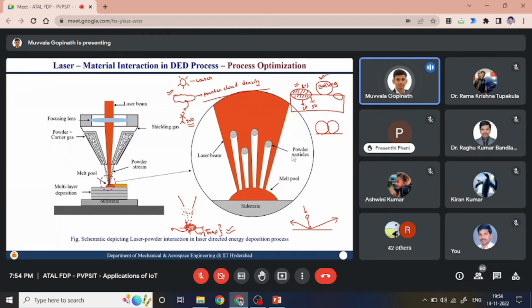Now this zone is what we call the shadowed region or the dark region, because when the laser is trying to fall like this, this particular bead is actually blocking the laser light from reaching this location. That is something which will lead to interrun porosity. Though there was some melting of the substrate, since enough heat did not reach the substrate, proper wetting will not occur, rather balling will occur.